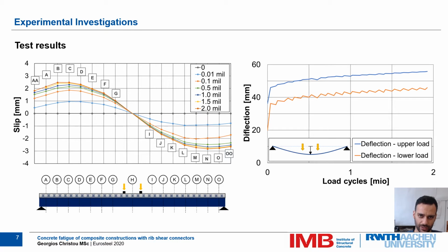The deflection of the girder shows the same principle. While in the beginning of the test the deflection increases significantly, we observe a very slow further increase of the deflection after approximately 0.5 to 1.0 million load cycles.